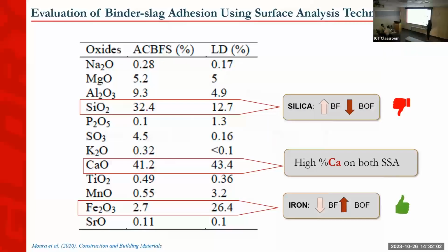And finally, we checked the chemical composition. This is the BF slag, and this is the BOF slag. We noticed that the BF slag, the iron slag, had a much higher silica content and lower iron content than the BOF slag, with more or less the same calcium oxide percentage. We know from the literature that silica aggregates are acid aggregates and don't have a good adhesion with binder. This makes sense when we look at the BF slag's amount of silica. Regarding iron, much literature suggests that the higher the iron content, the better the adhesion. It also makes sense from our observations. And calcium was the same, so this was not considered a variable.